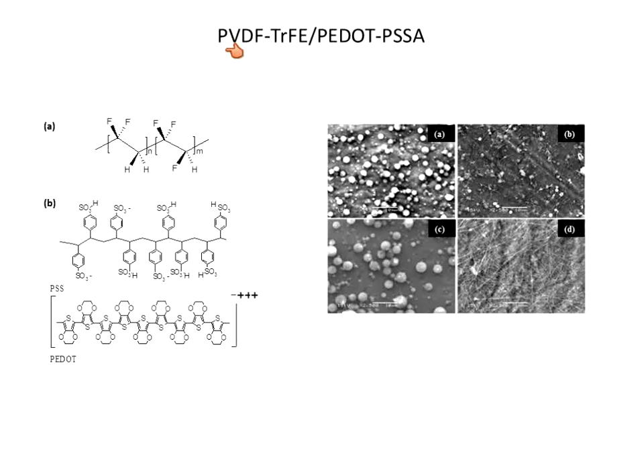Here, for example, is a polymer, polyvinylidene difluoride trifluoroethylene. So this is a ferroelectric polymer. So that's PVDF over here, and this is PEDOT over here, and this is a conducting polymer. So this is the polymer that does not conduct, this is the polymer that conducts. And if you were to just dissolve this polymer in DMF, for example, at three weight percent, and you do the electrospinning of PVDF in DMF, you see that there are no fibers, okay, so there are no fibers over here.